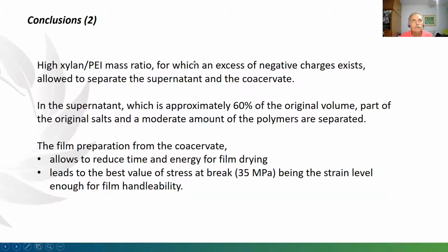High xylan/PEI mass ratio, for which an excess of negative charge exists, allowed us to separate the supernatant from the coacervate. In the supernatant, which is approximately 60% of the original volume, part of the original salt and a moderate amount of polymers are separated, and the film preparation from the coacervate allowed to reduce the time and energy for film drying, and leads to the best value of stress at break, that is around 35 megapascals, with the strain level enough for film handleability.